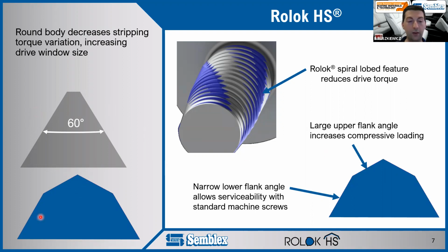Underneath that large flank angle, we have a much narrower flank angle. And what that lets us do is stay serviceable with standard machine screws. All that actually means is the pitch and our diameters of our Rolok HS screw match a standard metric machine screw. So if you form a thread with an M5 Rolok HS and you take the Rolok HS out, you can insert an M5 metric screw in its place and it'll work just fine.